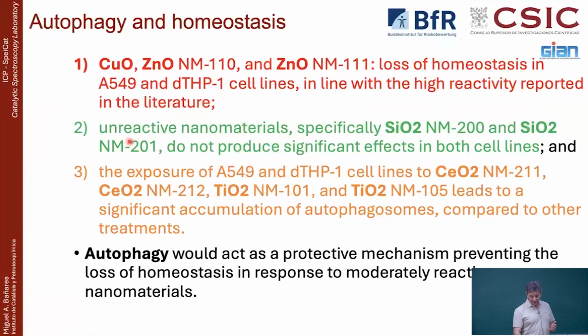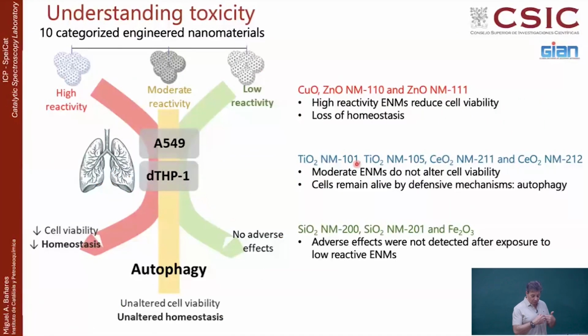So that was a little bit the classification of these materials. The most reactive ones damage the homeostasis in the cell for these two cell lines, which is in line with a very high reactivity. The unreactive ones have no effect, and the cells do nothing to compensate because there is no damage. And for the intermediate ones, there is some damage which is being compensated by the autophagosome.